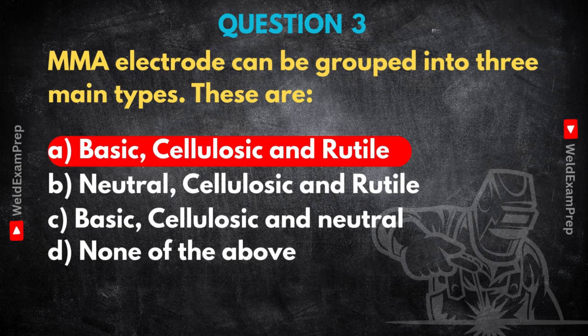Let's start with basic, often called low hydrogen electrodes, right? Their coatings produce weld metal with very little hydrogen. That's critical for stopping hydrogen cracking, especially in things like high-strength steels, pressure vessels, thick sections, really important stuff. What sometimes gets missed but is vital for an inspector is storage. They must be kept dry, usually in heated ovens. If you, as an inspector, see basic rods just lying around exposed to the air, that's a big potential quality problem. Moisture kills their low hydrogen benefit, introduces cracking risk.